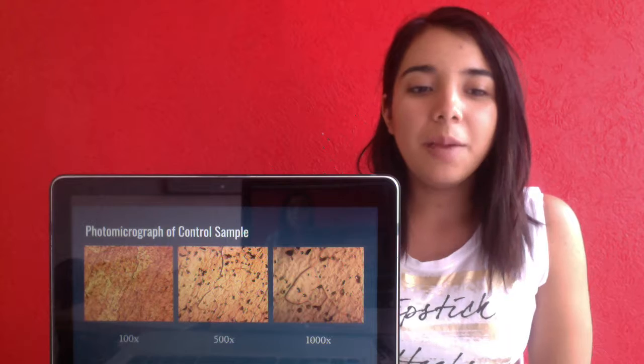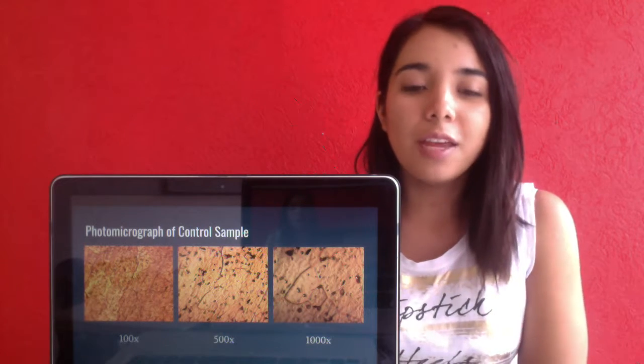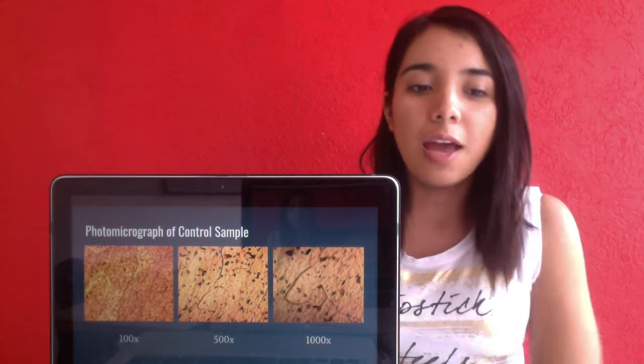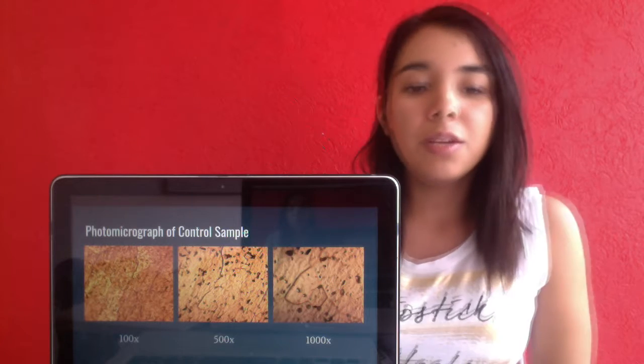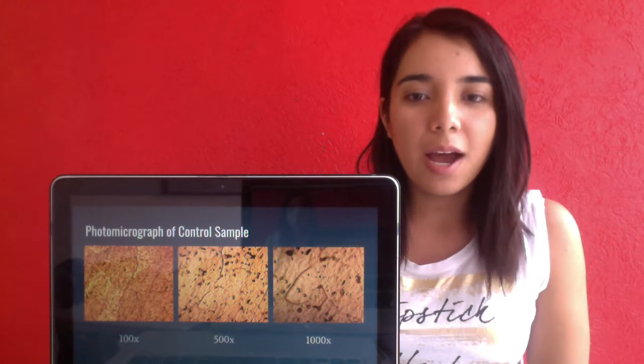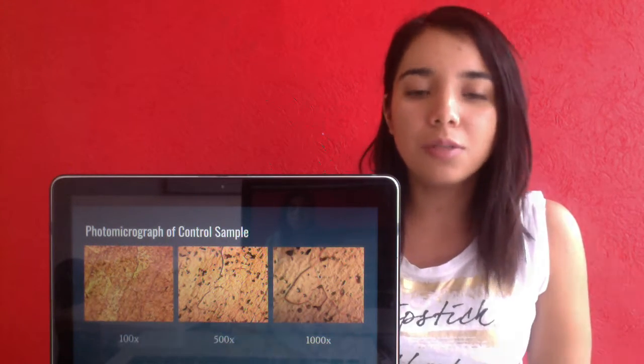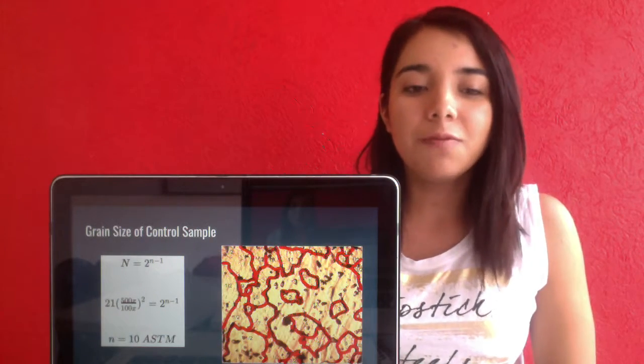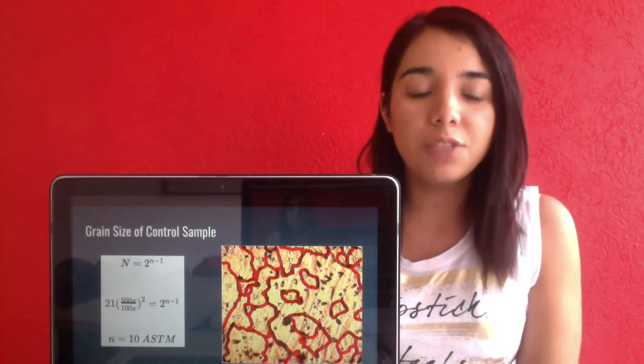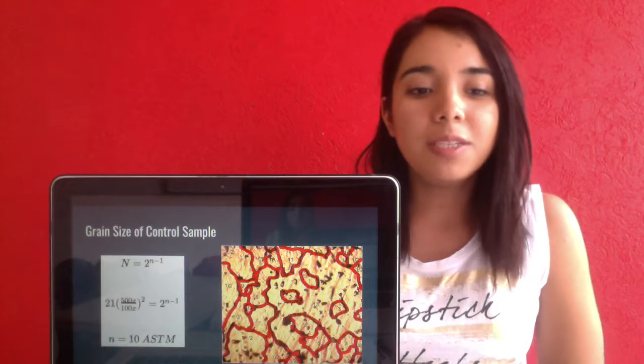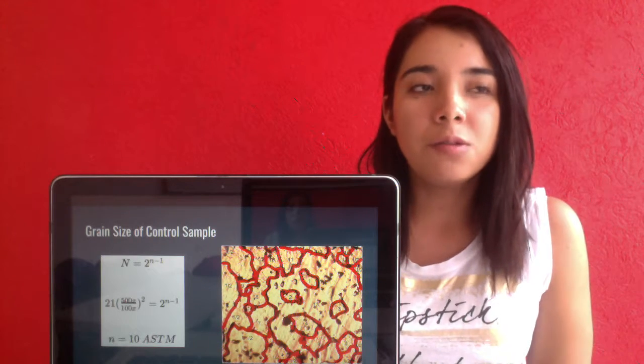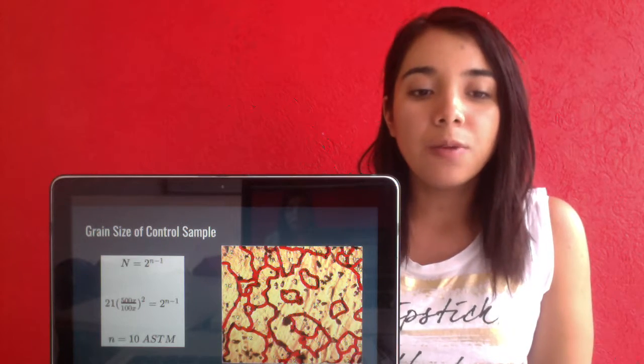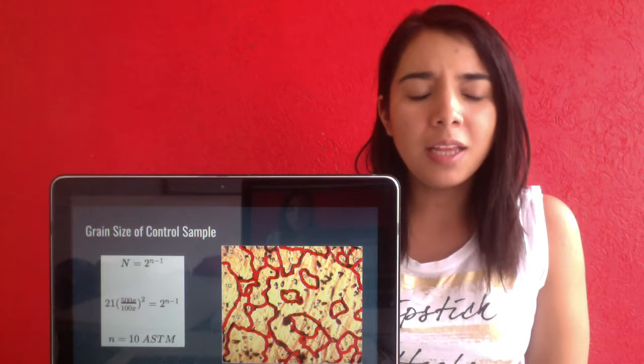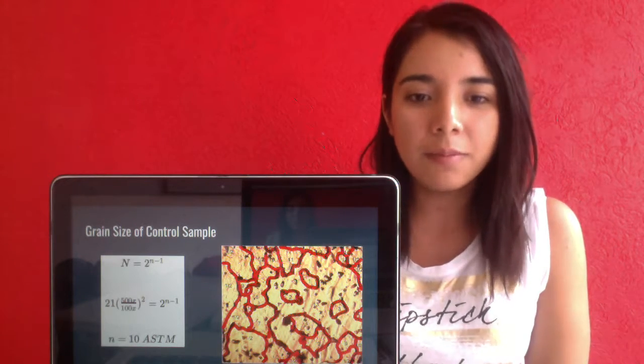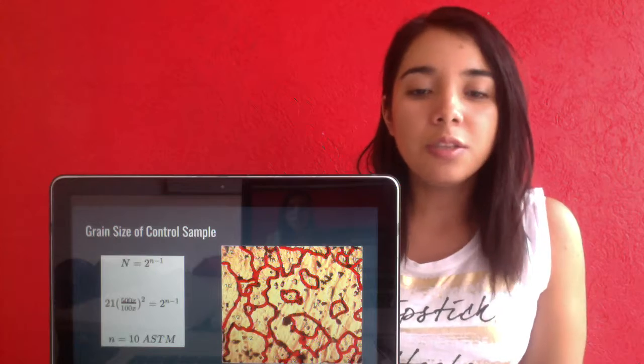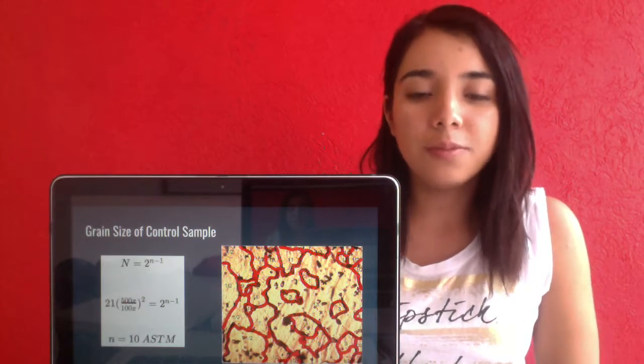We obtain the microstructure of the samples, and for the control sample, we use magnifications of 100, 500, and 1000. With the magnification of 500, we use the grain size formula, and we saw 21 grains, and we adapt the formula. We obtain an ASTM number of 10, which is a good number for aluminum.